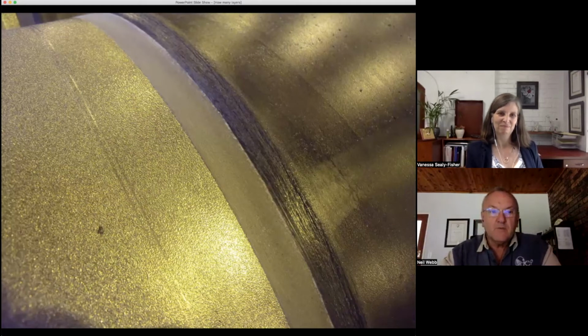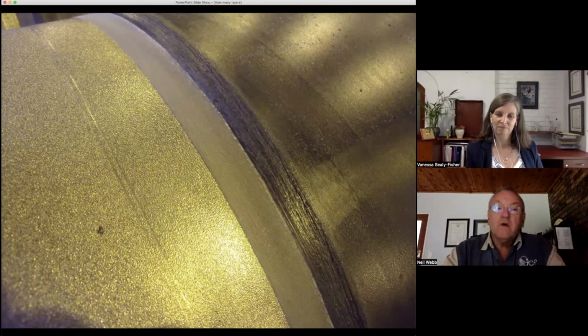And over the years, it was discovered that this led to disbonding between the system and the steel. And the systems over the years have gradually been improved, and it is now pretty much accepted that the epoxy inner layer has to be the equivalent of a standalone epoxy system if it's going to work underneath the polyethylene. Because even though polyethylene has a very low water vapor transmission rate, it does still allow water vapor through.